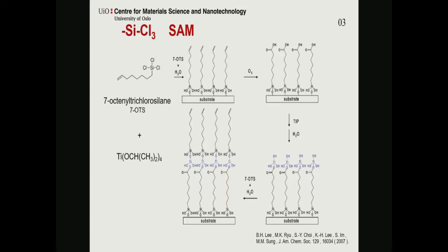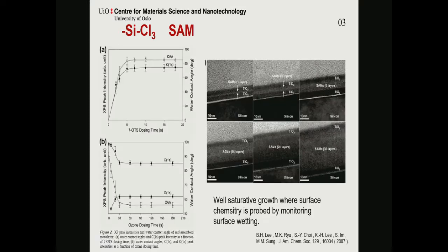Not so. There's a lot of organics which is resistant to ozone. It depends on the time frame, yes. But the double bonds are attacked much more quickly, and here you can reactivate the surface for another type of growth. This also works with the aromatic ring structures that you have. They tested this for controlling the wetting phase, and in this case they also monitored more or less by XPS the amount of oxygen and amount of carbon. So there are numerous ways you can monitor the growth itself.